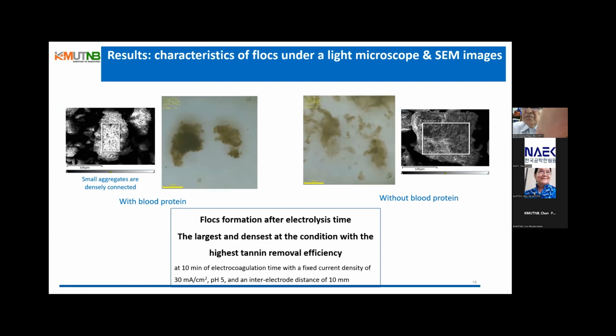These figures show the microscopic image of the flocs. The flocs from the system with the addition of blood protein were the largest and densest at the optimum electrolysis time of 10 minutes, at which the tannin removal efficiency was the highest. In contrast, the flocs from the system without the addition of blood protein were smaller and less dense. From the same image, the flocs consist of small aggregates that were densely interconnected.